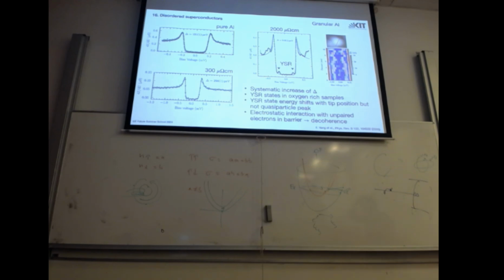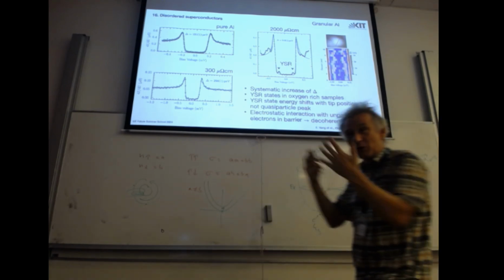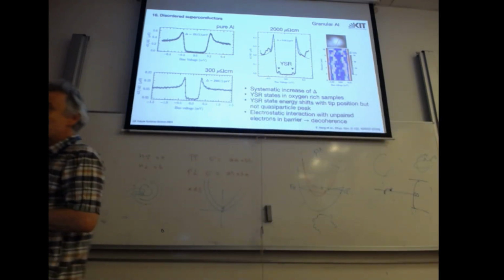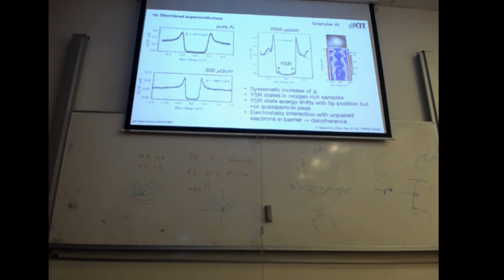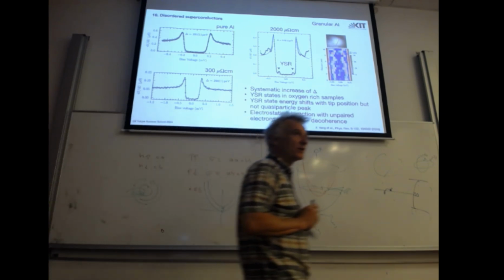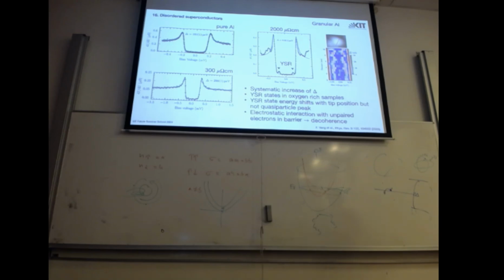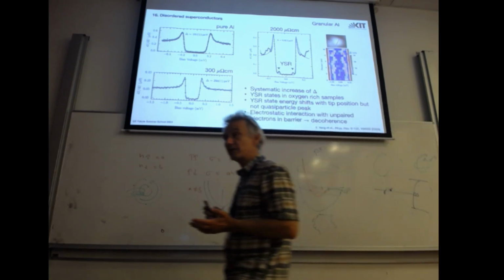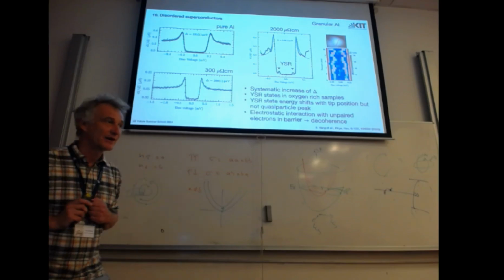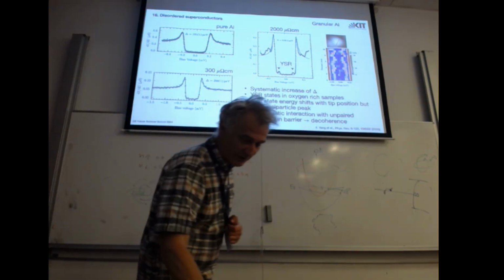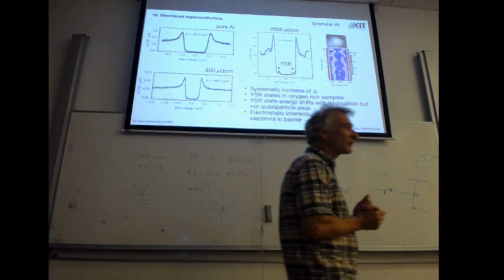Where exactly do the in-gap states come from? The only mechanism for in-gap states that I know of is YSR states. So maybe there are localized states. If you kill superconductivity and measure the resistivity of the samples, you will find that there's a Kondo effect. As long as you avoid superconductivity, there is a Kondo effect.